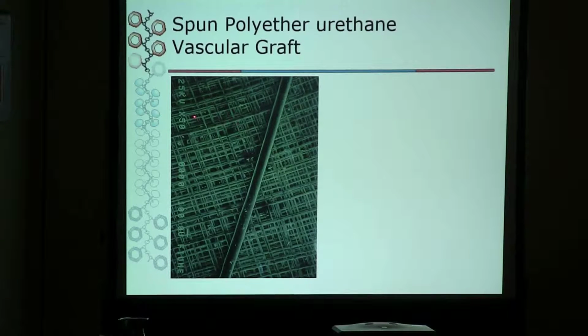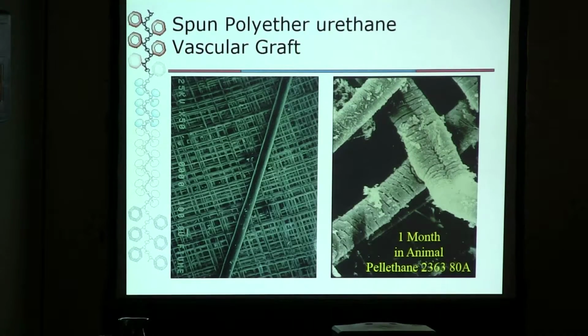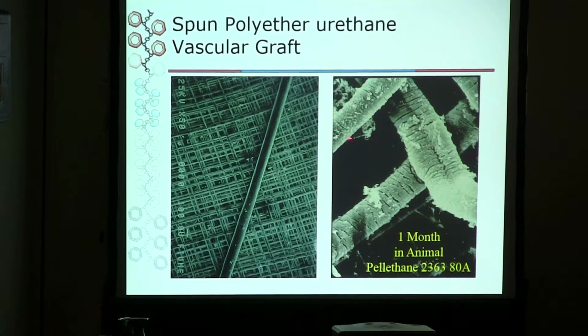And we used a material that is still used for pacer lead insulators. It's a polyurethane called Pellethane 80A. And we found after 1 month, these fibers all cracked. And very hard to get a company financed when that happens. So what's happening? And the mechanism was worked out by Jim Anderson's group at Case Western.